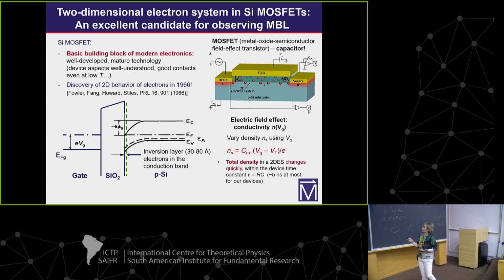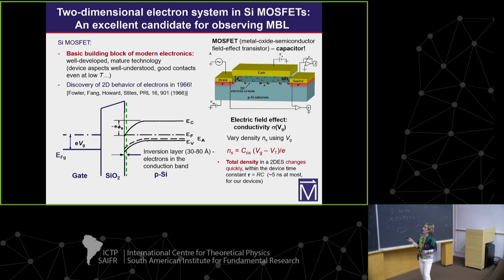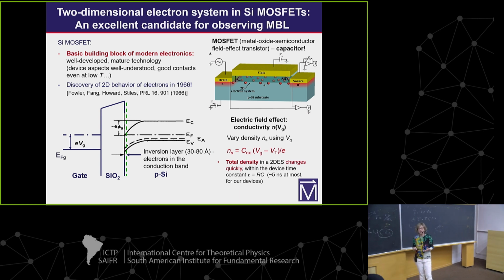And this is a process that is fast. It's determined by the capacitance of the oxide and the resistance of our 2D layer. Typically in MOSFETs, this is of the order of picoseconds or tens of picoseconds. In our case, for the largest resistance we studied, it's at most 5 nanoseconds. So this is all much smaller than our experimental resolution, which is about 1 or 2 seconds.